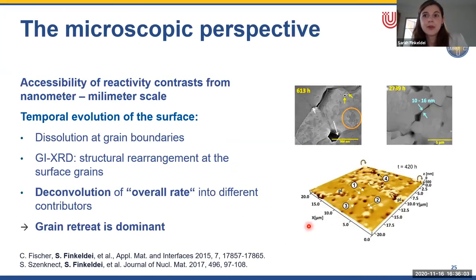In collaboration with the University of Bremen and the Institut de Chimie Séparative de Marcoule in France, I also performed microscopic experiments to understand how this dissolution actually proceeds. And we could observe grain boundary opening due to dissolution of those materials. With vertical scanning interferometry, we were able to understand that the main mechanism for the dissolution of those materials is grain retreat itself, so the grains dissolving themselves.